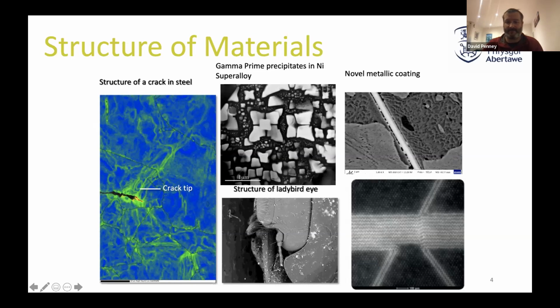And when we get to imaging, here's some pictures of some different materials at different scales. Here we have some steel, and using our microscopy techniques, we can see where the cracks are formed and also plot the stress area. So we can see where cracks might form, and you can see at these 3 points here where the grains are joining, there's extra high stress. So you might form a crack around here, or you might form a crack here.